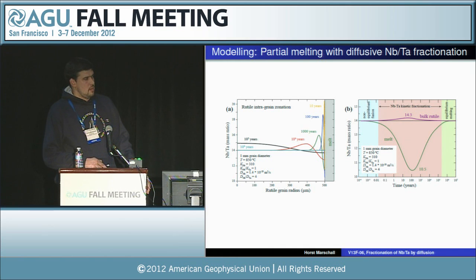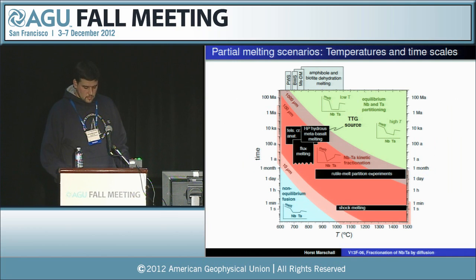So you generate very low niobium-tantalum ratios in the melt, and then as tantalum catches up, the thing goes back, and the yellow area is the equilibrium scenario. So over 6 orders of magnitude in time, we are kinetically fractionating niobium from tantalum and generating very low ratios in the melt. So this is my global plot showing time scale on the vertical axis and temperature here.